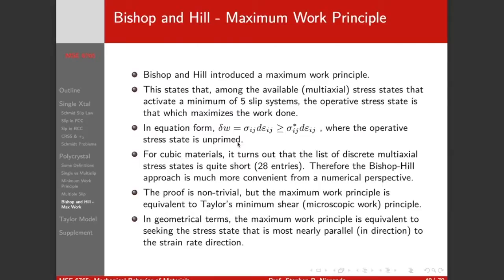Bishop and Hill are talking about stress — not about how the strain itself is partitioned. The stress state that activates a minimum of five slip systems: the one that is active is going to be the one that does the most work. What is work? Force times distance. In terms of vectors, it's F dot D — the projection of force onto the distance. So how do we maximize the work done for a given amount of force? We make it parallel with the deformation.